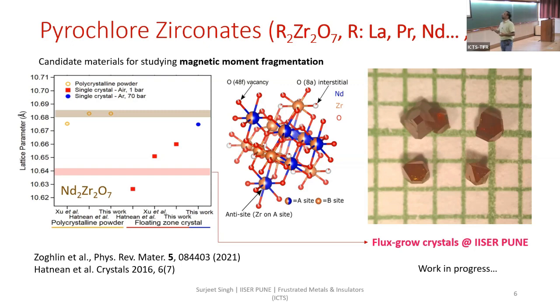Why are Nd and Pr important? Because both Nd and Pr have small moments, and Nd in particular is a Kramers ion. So you get the Kramers doublet, and you get an effective spin half on the pyrochlore lattice. This effective spin half in fact gets further fragmentized, giving rise to very fantastic physics, related to superimposed ground states with both spin ice as well as spin liquid kind of correlations present together.